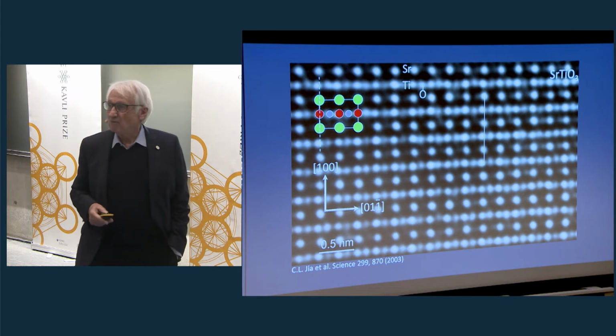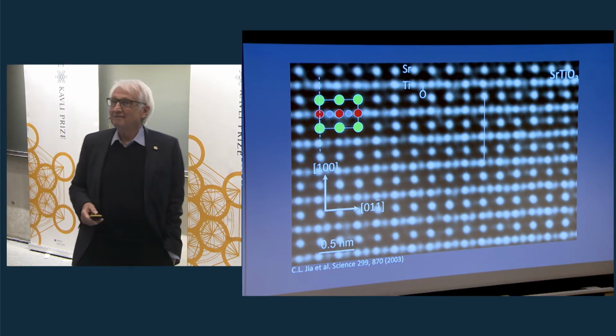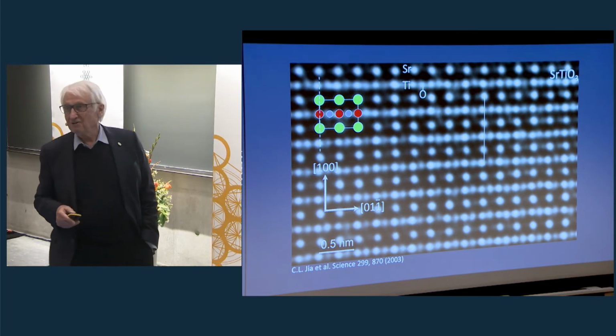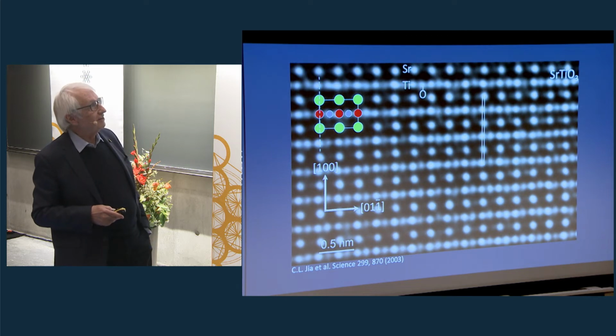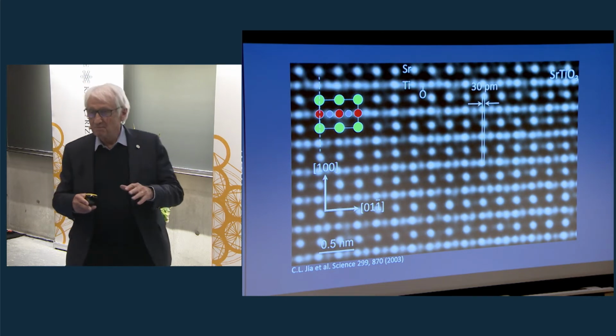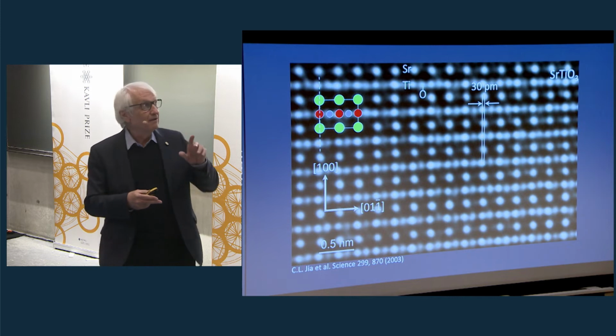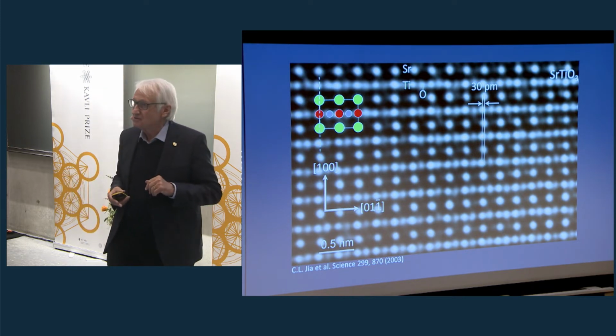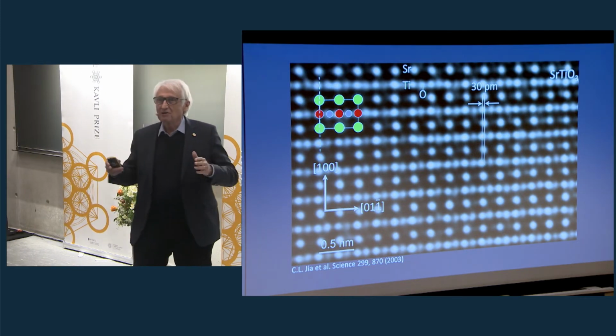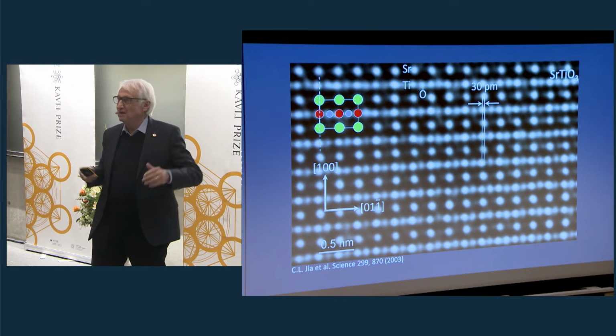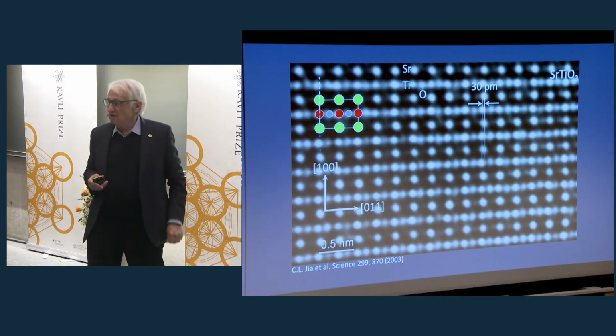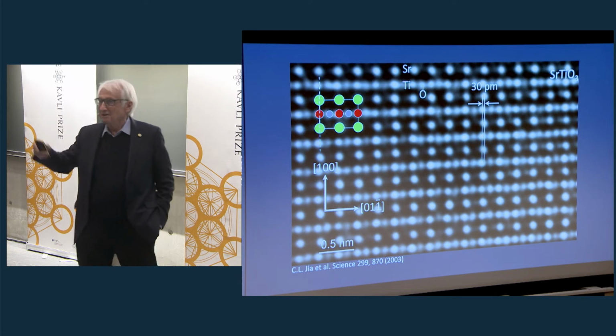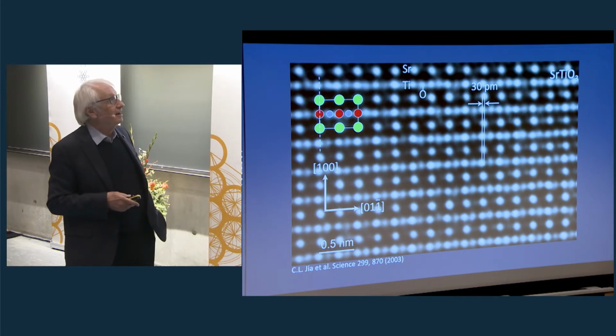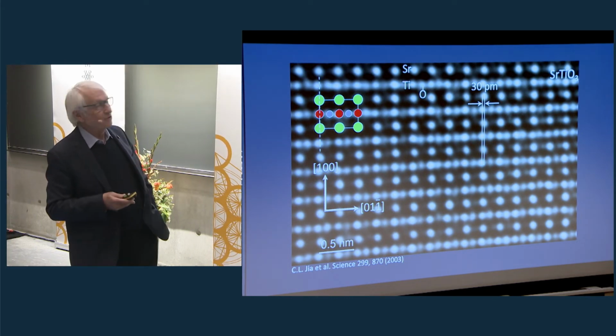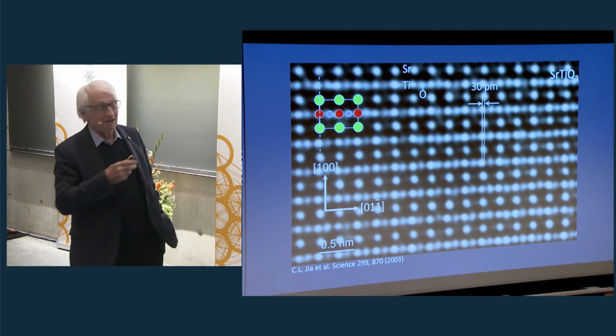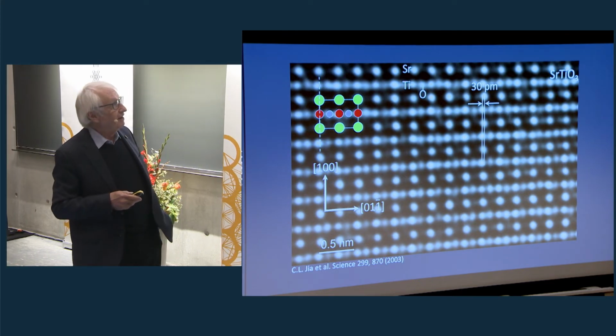So next Kavli prize, or even higher, because we have discovered something. You see that the titanium atom is shifting to the left by 30 picometers. When you have a microscope where you can essentially measure a few picometers, this is very, very real, or maybe the next prize. And of course, it's not dramatic because it's trivial what has happened here.